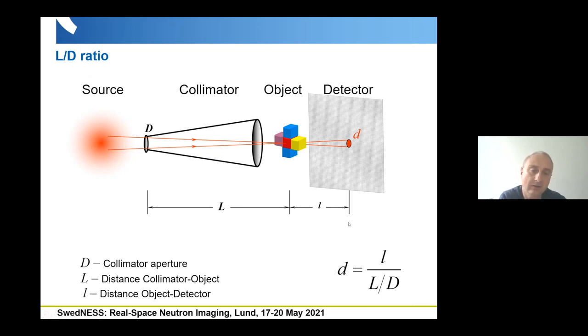And we can reduce this geometrical blurring or increase our resolution when we keep a very close distance between the object and the detector, or improve the properties of our collimator using a large distance or a small pinhole. Of course, reducing the pinhole or using a large distance will reflect on the intensity which we have at the sample position, or the number of neutrons which have this solid angle for reaching the sample. And therefore, this will result in increased exposure time. So finally, using a certain pinhole is an optimization question, where the exposure time should be feasible for the experiment we are going to perform.